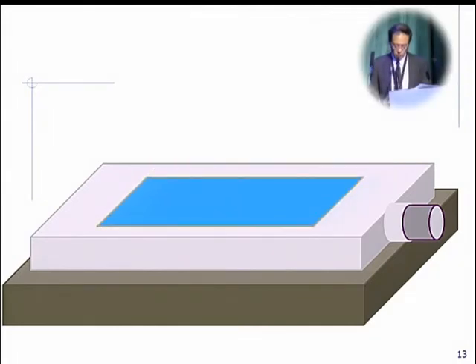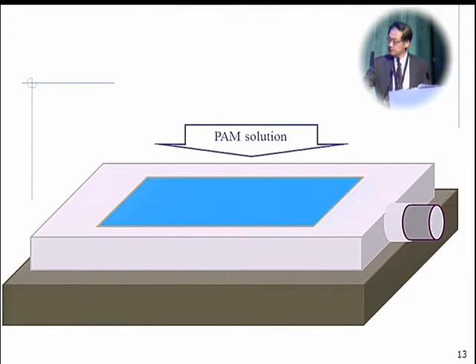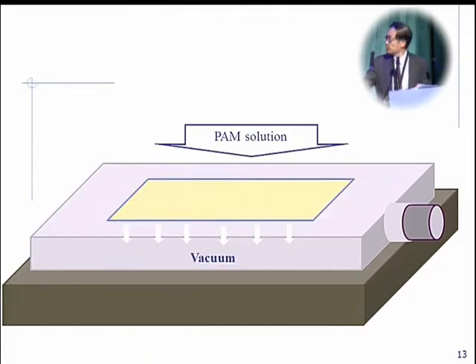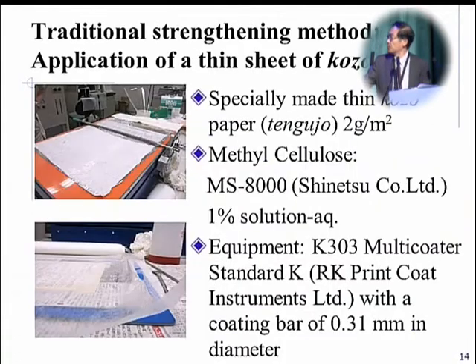A dilute solution of polyacrylamide is applied all over the non-woven sheet and suction is applied. Once the fleece layer has adhered to the sample paper by means of the applied suction, we remove the non-woven sheet from the paper and the strengthening treatment is completed.